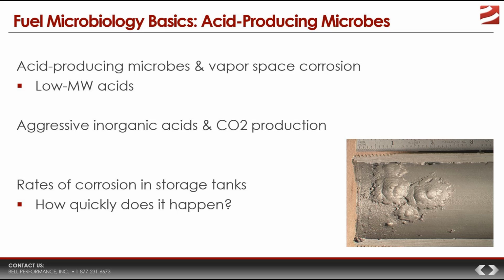So how quickly does corrosion happen in a typical tank? Well, the average literature value for corrosion rates is about 0.3 to 0.5 millimeters per year, and this is for diesel tanks. Gasoline tanks actually have lower corrosion rates, only around a tenth of a millimeter per year. Now, part of the nature of the tank corrosion damage, fouling, and microbial-induced corrosion, or MIC, that we've been talking about is that you rarely will find it unless you are actually looking for it. That means you rarely find corrosion damage before it has developed to the point where the problems are obvious. That fact gives us an excellent reason to look closer at the essential practice of condition monitoring in our fuel storage systems. So that is what we are going to transition to next.